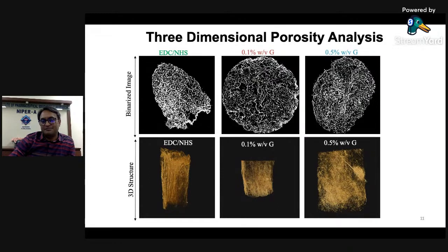For that, we did the microCT analysis. This analysis gives us deeper insight about the material properties. Most of the material looks the same in this binarized image, but when we reconstruct into three-dimensional form, you will see that only collagen cross-linked with EDC shows more fibrous-like nature in the hydrogel. However, this fibrous nature is lost when we incorporate 0.1% graphene and 0.5% graphene.